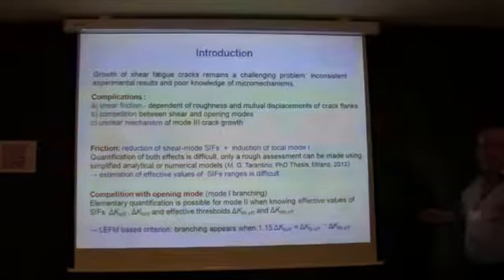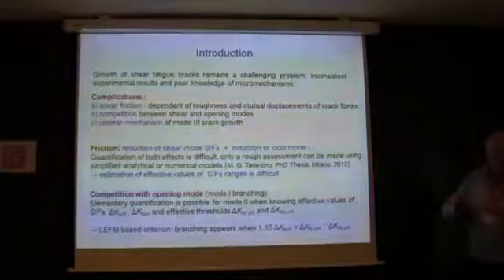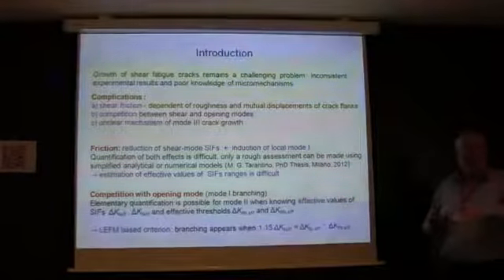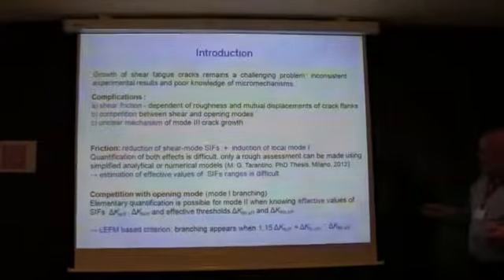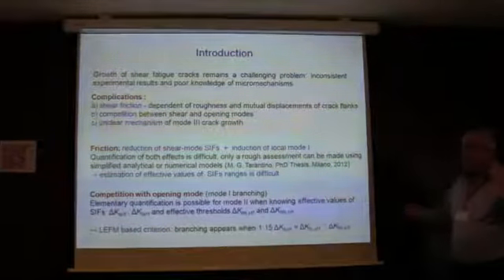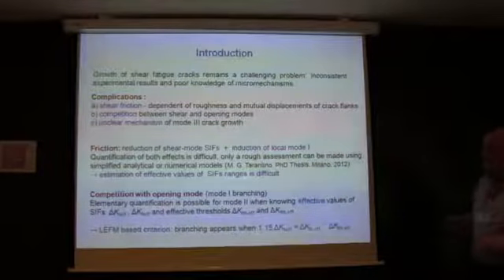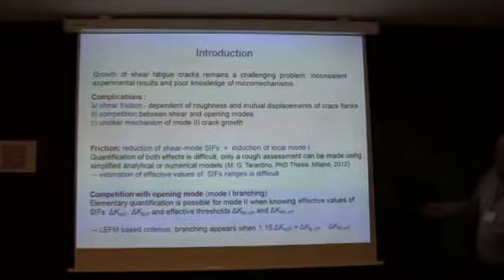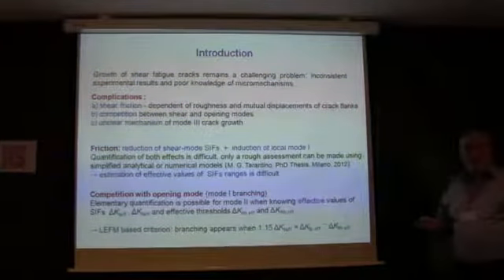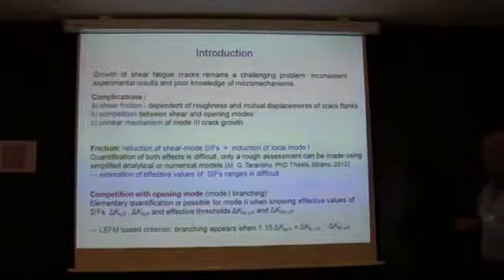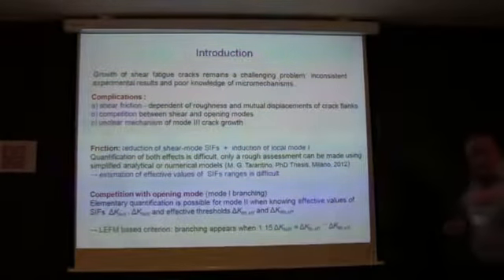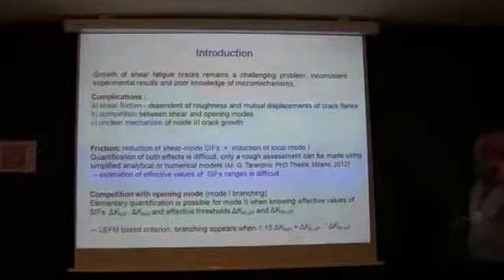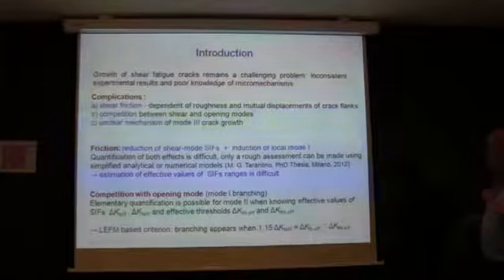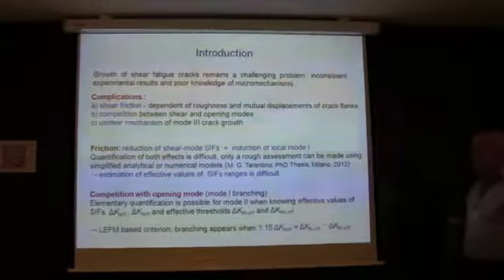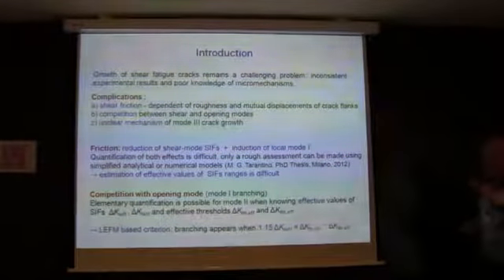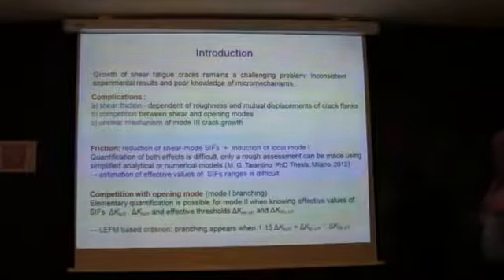Then there is a competition between shear modes, especially both shear modes 2 and 3, and mode 1. And there is a more or less unclear mechanism of mode 3 crack growth in the shear case. Actually, friction reduces the stress intensity factors at the crack tip, and moreover, it induces a local mode 1. So this is a quite complicated case, and the quantification of these effects is difficult. A rough assessment can only be made using analytical or numerical models.